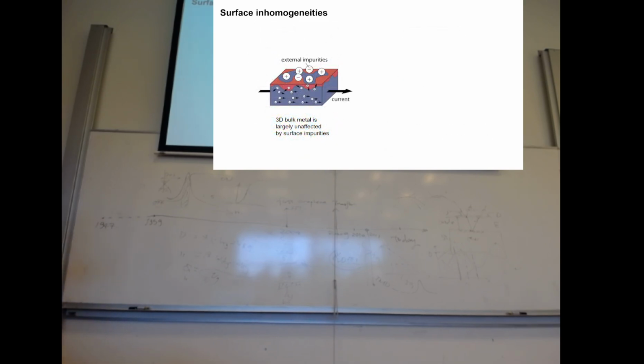And then there are ways to, for example, for 3D bulk material, there is only one surface on top. So some kind of impurities are screened, and they cannot influence the inside body transport. But for two-dimensional systems, it's all surfaces. So we cannot avoid any kind of impurities because long-range and short-range scattering can both degrade your transport properties.